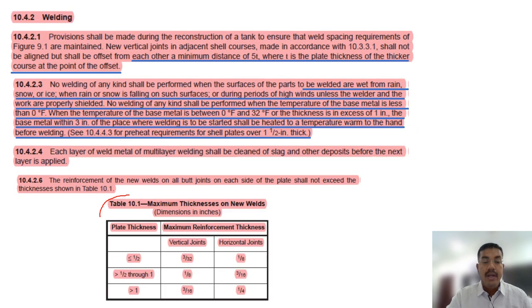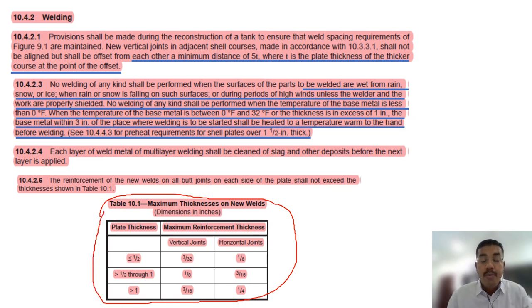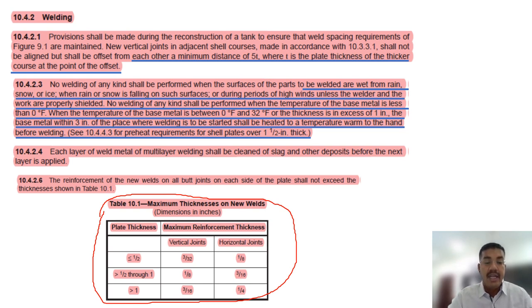This welding table is both a close-book and open-book question. There are two things: reinforcement for visual inspection and reinforcement for radiography — do not confuse them. For radiography and visual inspection, the requirements are different. In an open-book question, if they ask for the minimum reinforcement thickness in a vertical joint for plate thickness less than half inch, the answer is 3/32 inch.